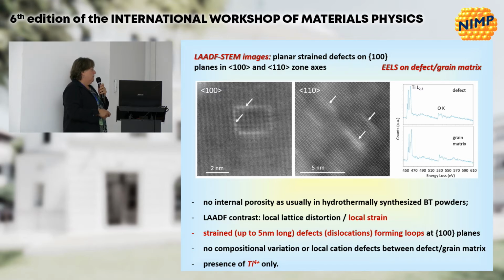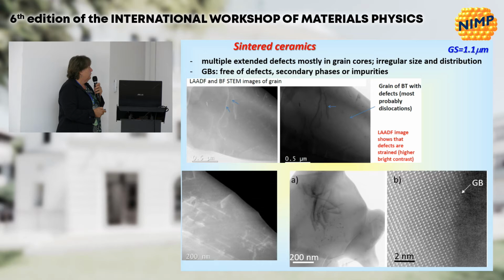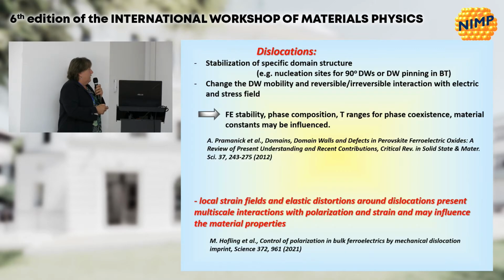They are about 5 nanometers long, and they form closed loops. And again, the presence of titanium 4+ only. Further, with these powders, we have the ceramics. The sintered ceramics show internal defects mostly inside the grains, which look like dislocations. They are irregular in size and distribution. At the boundaries, none of these defects was found. It means they are in a way released or compensated, and the grain boundaries are very clean and separate regions of single crystalline character.